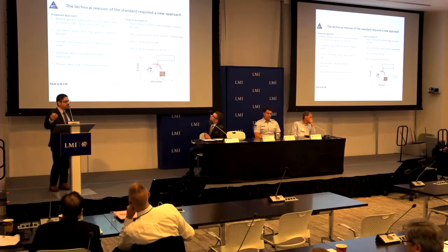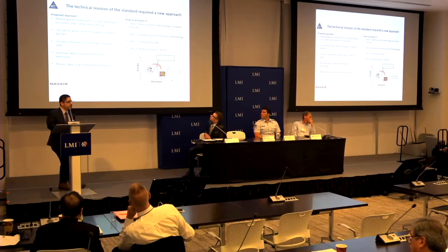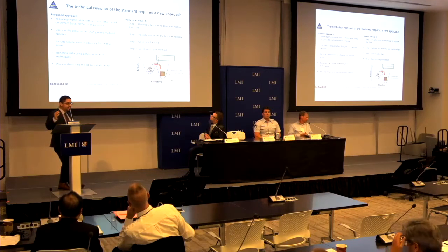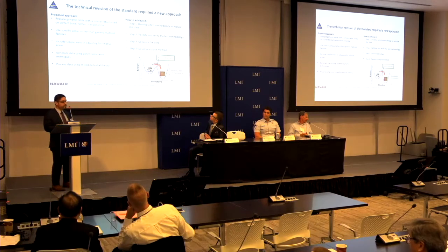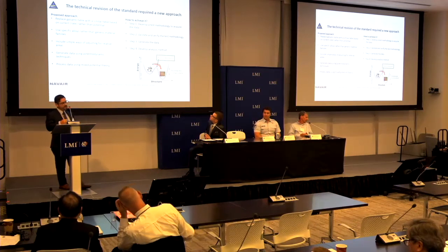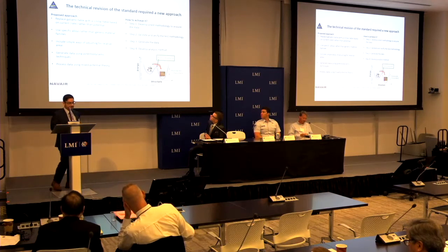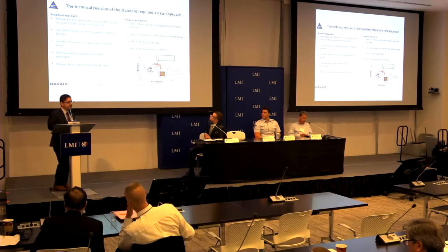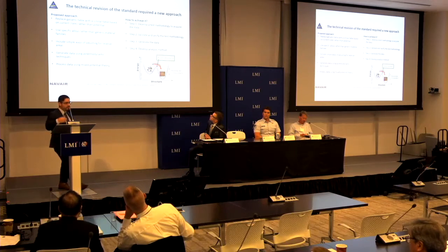So the technical revision obviously required a new approach. Basically, what we wanted to do is replace the galvanic table with a similar table based on current or rate as opposed to potential. Use specific alloys rather than generic materials families. Include a simple way of adjusting for areas, right? It's different if you have a big component or a small component. The area matters. So we included that in there. Generate data using potentiodynamic techniques and process the data using available theories.